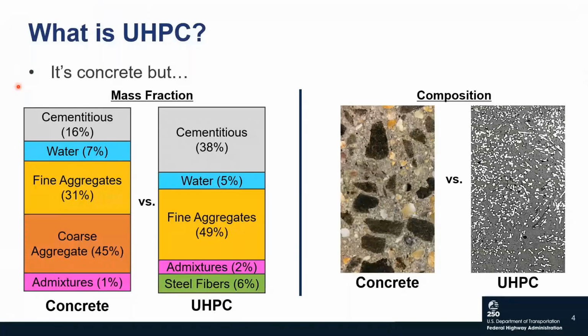The image on the right-hand side shows a microstructure view of conventional concrete compared to UHPC. So you can see here the coarse aggregate, typically about 1/4 inch to 3/4 inch in size. You won't see that in UHPC given that it does not have any coarse aggregates. What you'll see are those shiny dots on the UHPC picture. Those are the steel fibers in the matrix. Typically, steel fibers are included at 2% by volume.